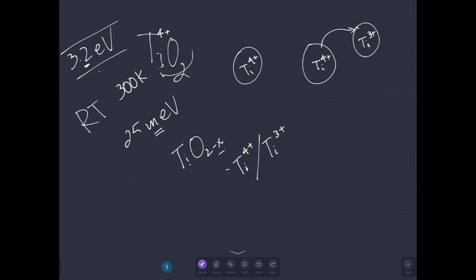And so, while this material is normally an insulator, this becomes an N-type semiconductor. So by this controlled atmosphere processing, you're basically converting an electrical insulator into a semiconductor. Now, if you're dealing with silicon and germanium, small band gap materials, it's a different way of making semiconductors. This is a high band gap semiconductor - what is the advantage of a high band gap semiconductor?